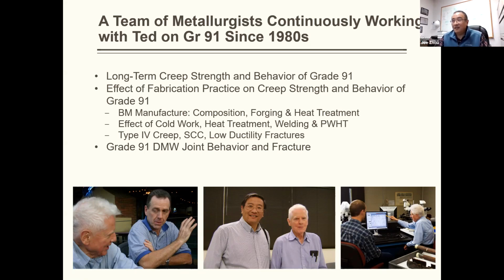So then when you talk about welds, you have Type 4 creep damage, stress corrosion cracking, low ductility, fracture behavior. And in the last 10 years, people are seeing more and more failures on the Grade 91 DMW joint. So this is now a hot topic.